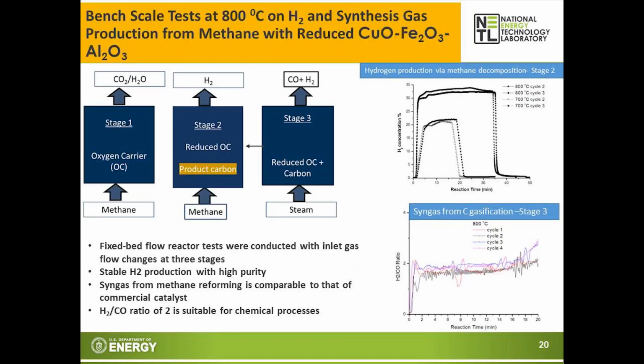We have conducted bench scale tests at 800 degrees C to evaluate this process of methane decomposition. Here, in the initial stages, the oxygen carrier reacts with methane to produce CO2 and water. In stage 2, when methane is introduced to the reduced oxygen carrier, it produces carbon and hydrogen.